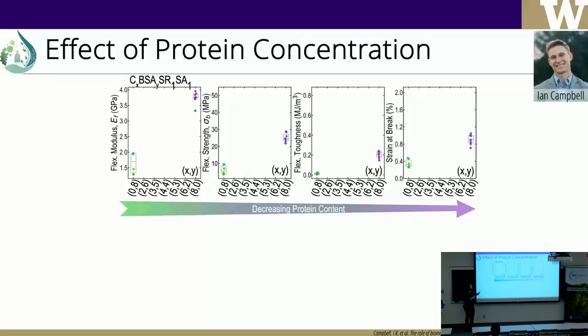In this case, we are fixing the small molecule concentration at 10%, and we are going to be changing the ratio between our protein and cellulose. So all the way to the left, we're going to have only protein, no cellulose, and your small molecules. All the way to the right, we're going to have just cellulose, no protein. Decreasing protein content. So maybe as you would expect, when you just have cellulose and the small molecules, your material is going to be very, very stiff and stronger than if you were to have just the protein. So the two extreme concentrations are as we expect.